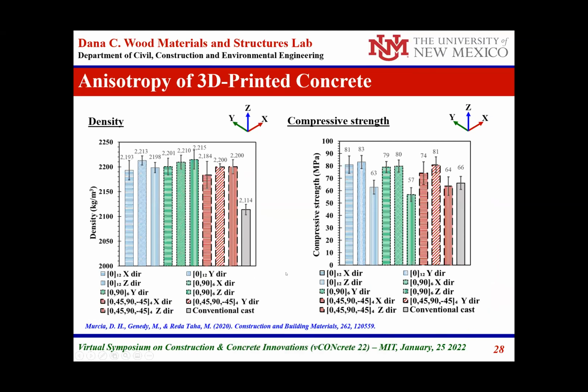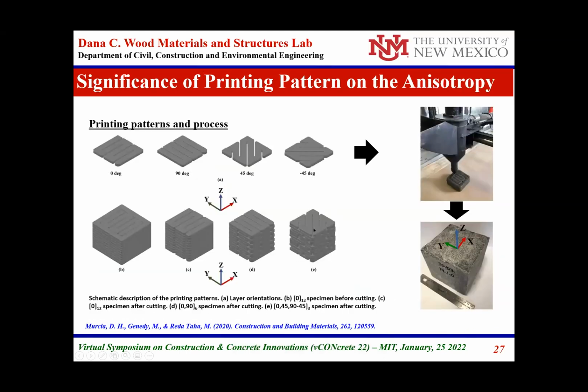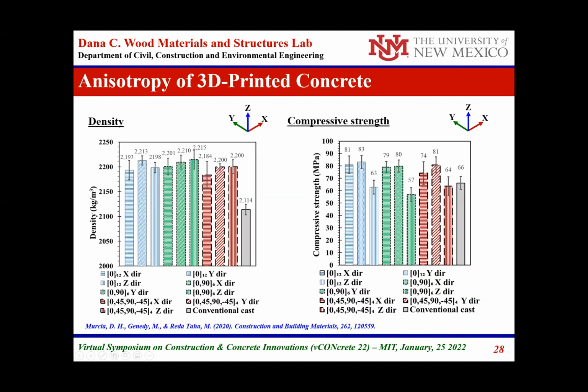Using this, we can quantify the effect of those interfaces on the concrete's capacity. We printed many concrete samples, some in the 0 or X direction, and tested the density and compressive strength. We also tested conventional cast concrete made of the same exact mix. In almost all directions, independent of direction, the density of the 3D printed concrete is a little higher than the density of the conventional cast.